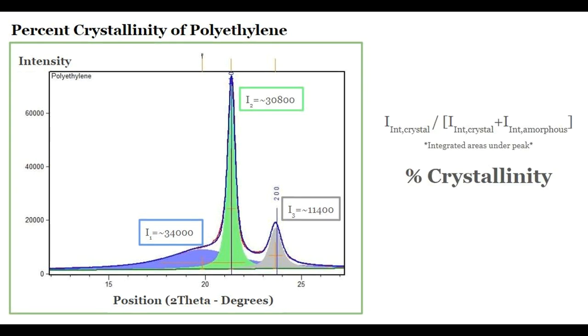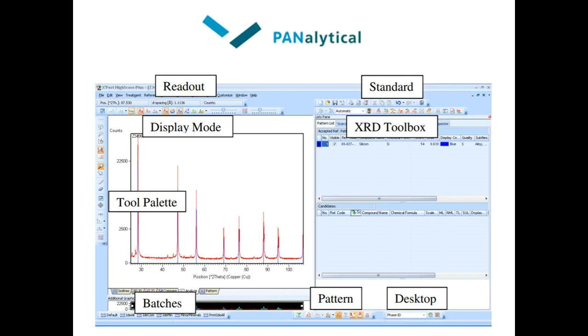The degree of crystallinity can be determined using this formula, where the total integrated intensities of all of the sharp peaks are divided by the integrated intensities of all peaks, including that of the amorphous peak. Many laboratories have access to XRD peak fitting software that can be used to calculate degree of crystallinity, but this software can often be expensive.